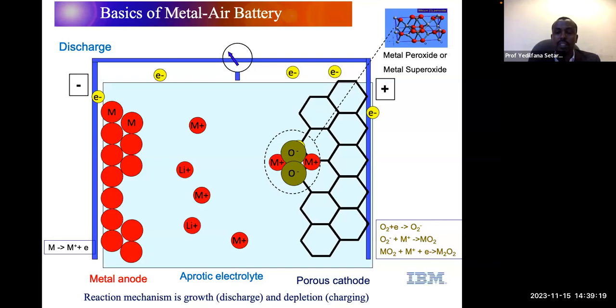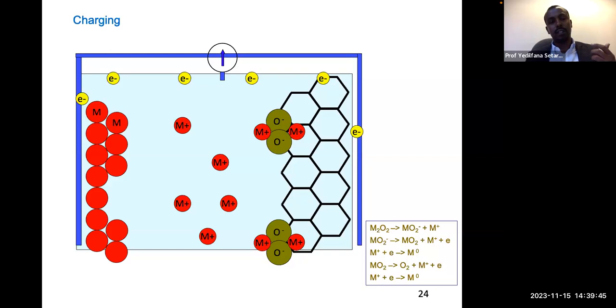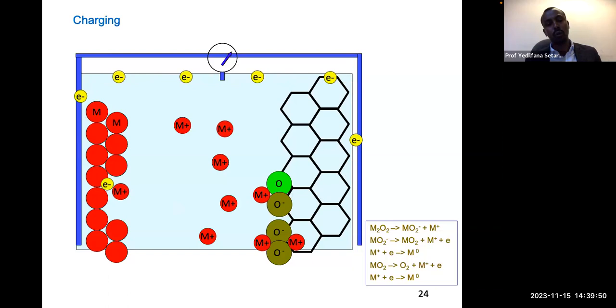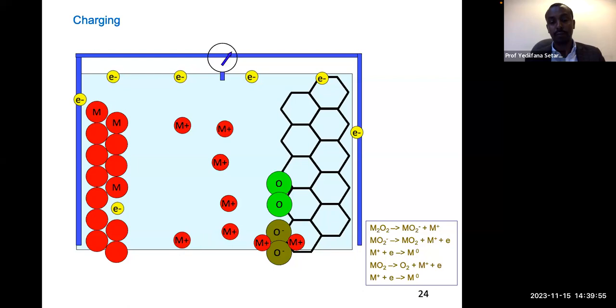So our cathode in this case is oxygen, right? It inhales oxygen from the atmosphere, and we only carry the lithium as the active species from the anode side. Lithium gets oxidized at the anode, the electron goes to the external circuit, the lithium ion goes through the electrolyte, and combines with the reduced oxygen to form a lithium oxide compound. During charging, oxygen will evolve out, and the ions, or the active species, go back to where they were and store at the anode side, right? And oxygen will evolve out. So this is the typical metal oxygen battery working principle.